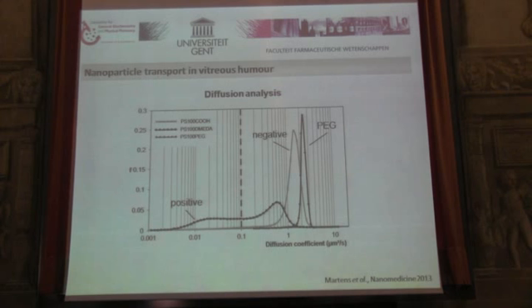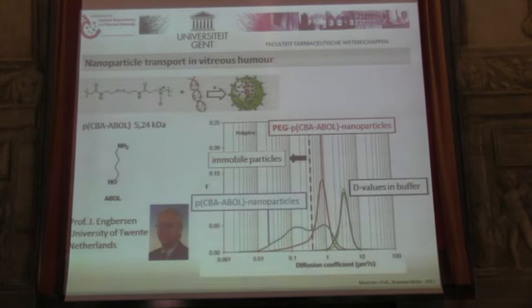So when the particles are injected, if they get coated by the negatively charged hyaluronic acid molecules, before they bind to a collagen fibril, they have a protective coating that keeps them mobile. And this is a strategy that we are currently pursuing to replace PEG by hyaluronic acid coating indeed. This was also applied to actual carriers, not just model particles. So this was in collaboration with Professor Engbersen. Many people will know him, I'm sure.